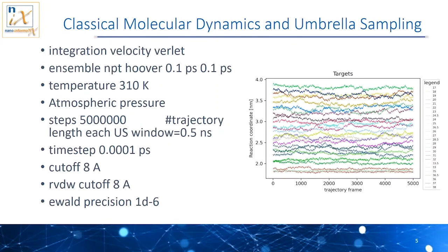The first thing to do is to choose the proper reaction coordinate to get the right information. In this case, I want to get the free energy for the aggregation of two nanoparticles at a specific distance. To do so, I set as a reaction coordinate the center of mass distance. I divide this distance the nanoparticles have to cross into target distances.